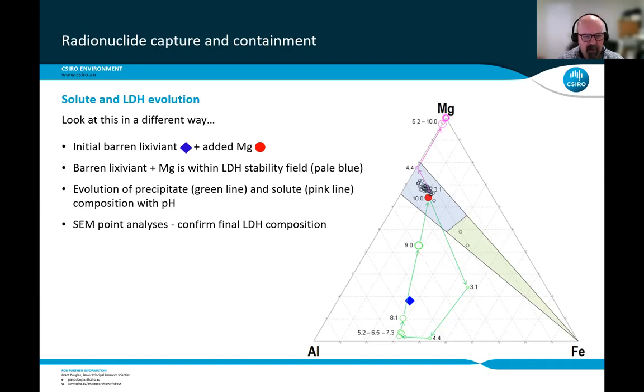Then once we start increasing the pH above 7.3 through to 8.1 through to 9 and then up to 10, as you saw previously, we start adding magnesium that starts to precipitate out, and we end back up pretty much where we started. So we've precipitated everything out in terms of the magnesium, the aluminium, and the iron. And you can see all those little open dots there. They're SEM point analysis, and they confirm the final layered double hydroxide composition, which is pretty close to where we actually started. So job completed, that's what we wanted to see.